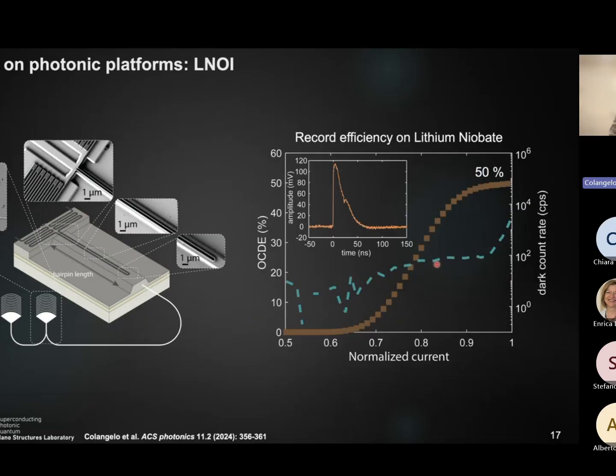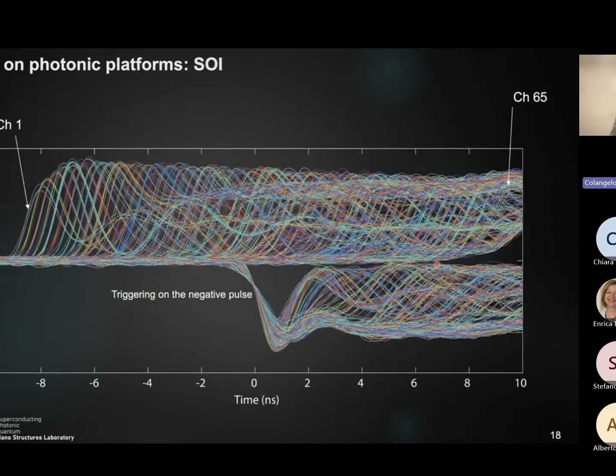So I'm showing here, sort of for the first time, an interesting plot where we see a differential signal. We have a negative pulse and a positive pulse. We are triggering on the negative pulse. And as you can see, you can count 65 groups in that positive pulse, which gives back a detection in 65 channels, which are time multiplexed. So this is an SNSPD fabricated onto an SOI platform where we have 65 channels all spaced together in a time multiplex approach. And it's the largest monolithic integrated array ever fabricated.